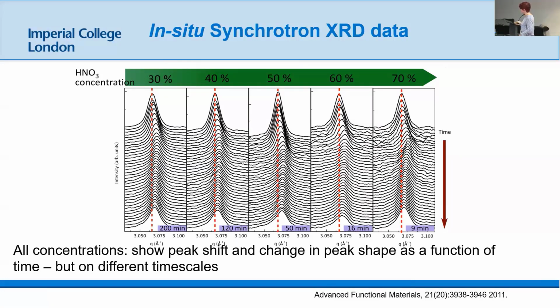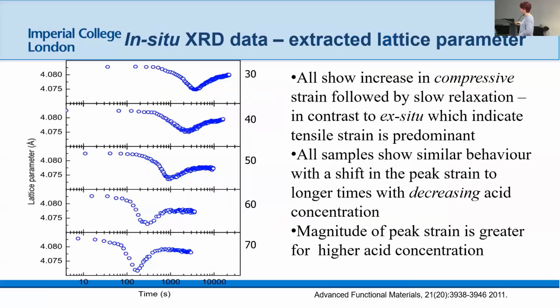Right. So if I show you the extracted parameters from that, this is the lattice parameter that we extract from those diffraction data. And what you see is, this is where we started, this is where we finished, some relaxed state, but there's a huge strain that builds up in the material as we form these nanoporous structures. And it's a huge percentage strain comparatively to the material.